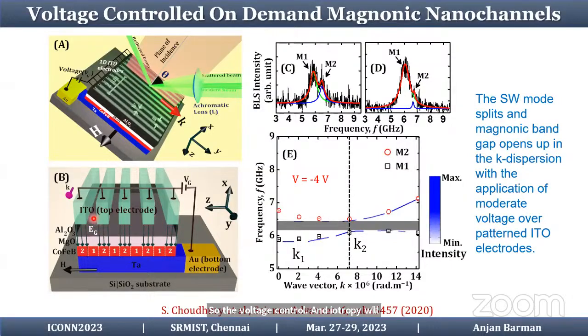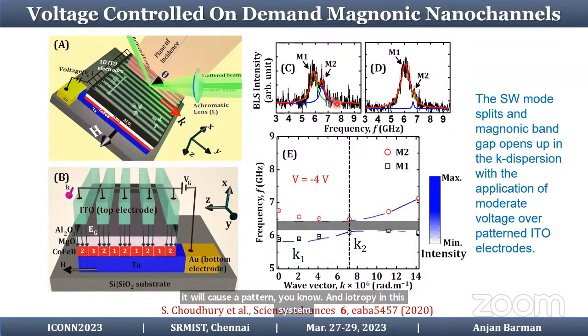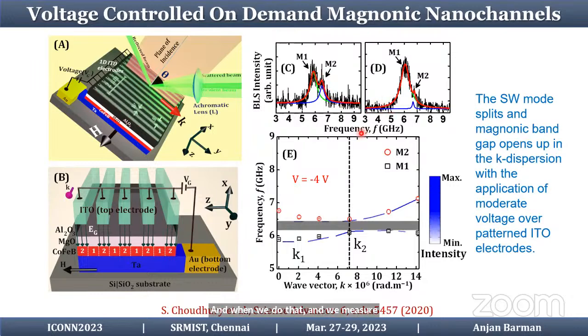So it will cause a patterned anisotropy in this system. And when we do that and we measure the spin wave, we can clearly see that there are two different modes in the system instead of a single mode. And when we plot their frequency as a function of the wave vector, we see that there is a clear valence band and conduction band kind of system, and there is a band gap.